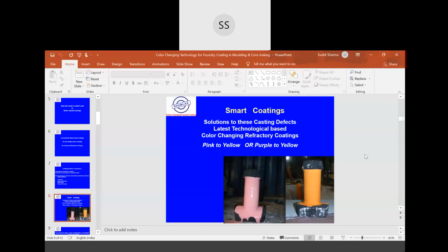And there are two types of coatings, particularly for most of the sand systems. If you consider a coating which is pink in color, which will dry to yellow, or the second coating which is purple in color, which will dry to yellow. It will cover almost most of the resin sand systems like your phenolic acid cured, alpha set, cold box resin systems.